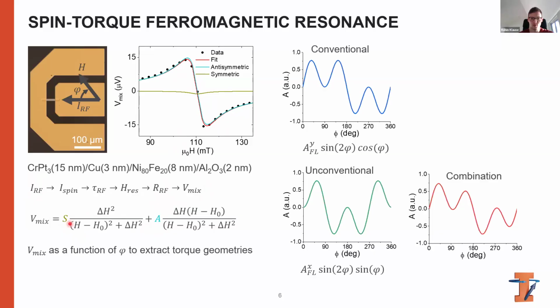And then we can do this whole measurement as a function of the angle between the RF current and the magnetic field, and that allows us to extract the torque geometries. So for only conventional torques, we expect the sine 2 phi cosine phi behavior of the antisymmetric component as a function of the angle. For the unconventional part, which would be a spin polarization parallel to the current, we expect the sine 2 phi sine phi behavior. And then for a combination of the two, we get something that combines both angular dependencies.